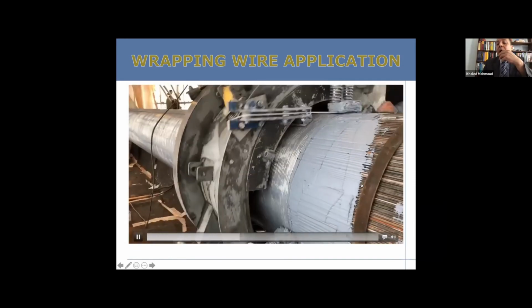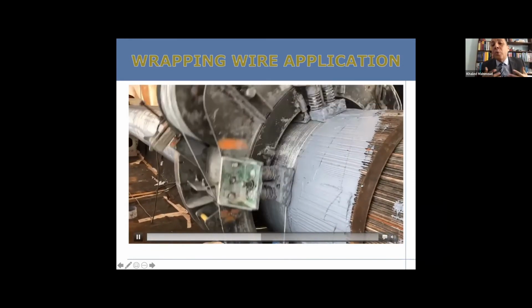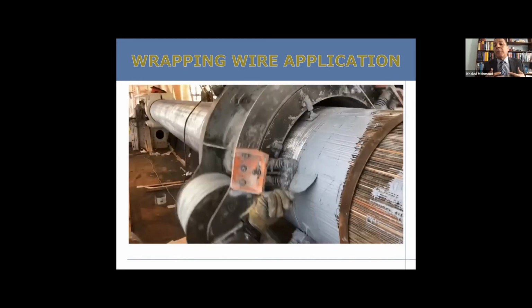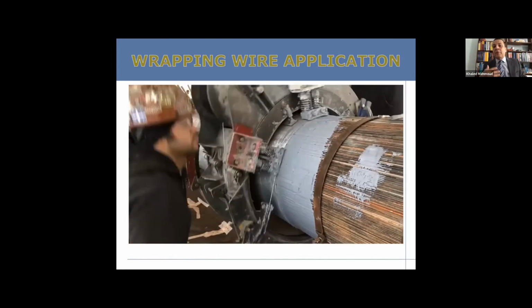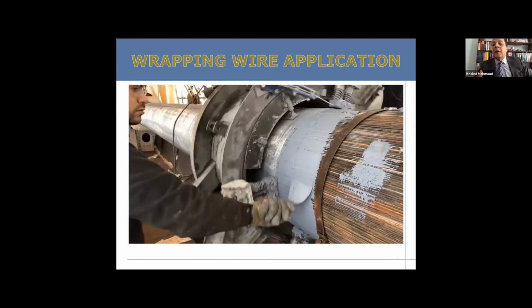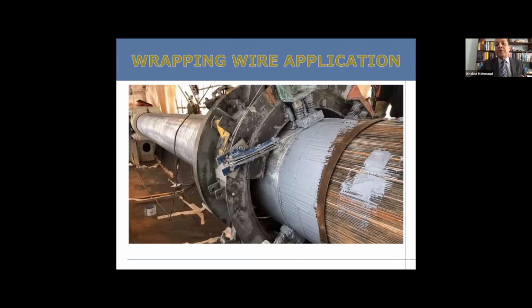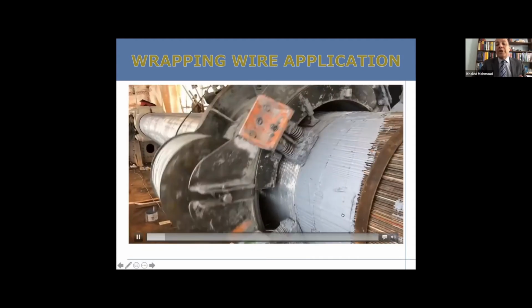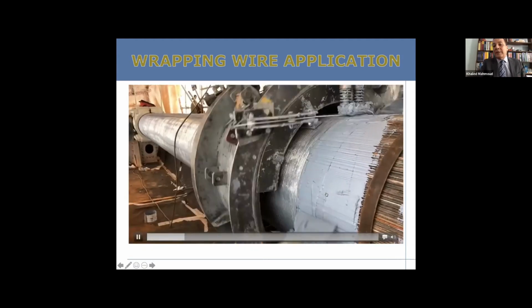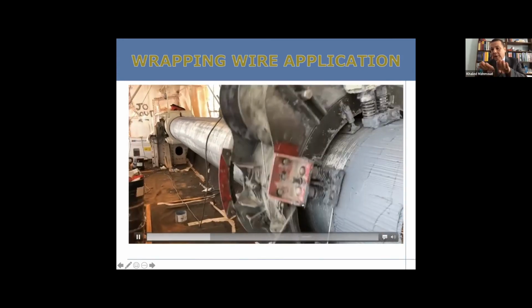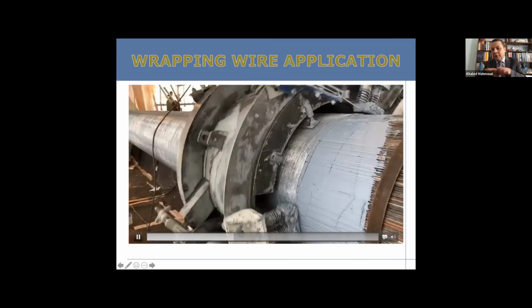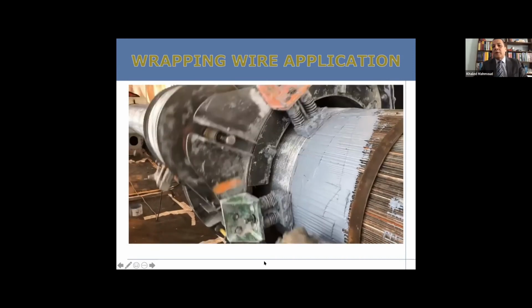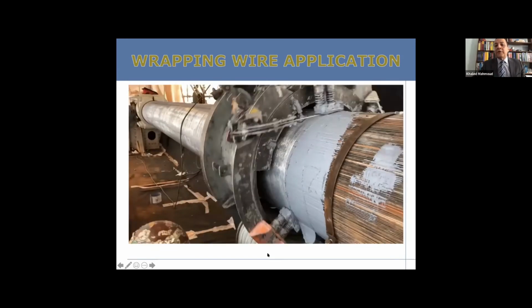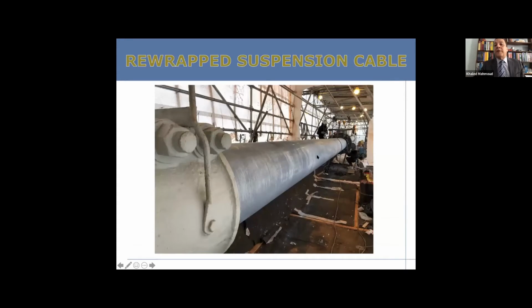You'll notice here that we are using a paste material. This paste material goes a long way in providing a moisture barrier and basically minimizing the effect of moisture on the bridge, damaging the bridge cable. So you apply this and you see the wrapping wire coming very close. The laps are very close to each other. And then afterwards, you will see a picture of the entire cable after the wrapping.